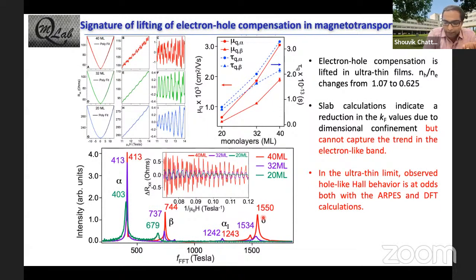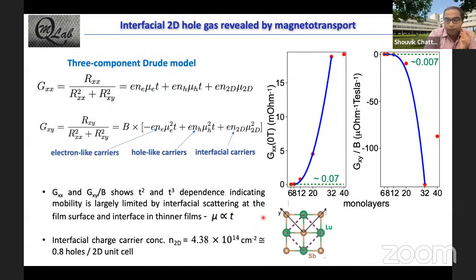So now for that, I want to remind you that when we grow our thin films, they are not freestanding, but we also have a substrate. So thereby we also have an interface. So what we try to do is analyze our data by utilizing a 3-component Drude model, where you have a component from the electron-like carriers, another from the hole-like carriers, and also some interfacial carriers. And when we analyze it, we can clearly see that we have quite a large concentration of interfacial charge, which is of the order of 4.38 times 10 to the power 14 per centimeter squared. That roughly translates to about 0.8 holes per 2D unit cell. And the 2D unit cell, we define it like this here, this violet dotted line, which has 1 lutetium, 1 antimony atom per unit cell.